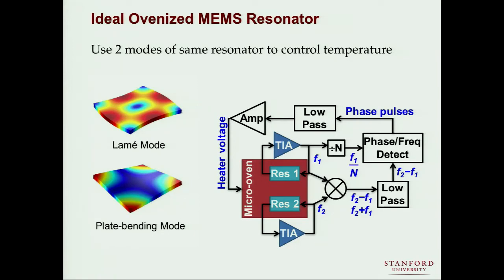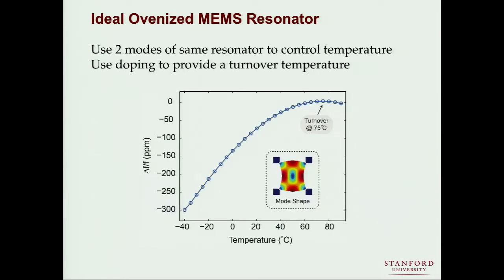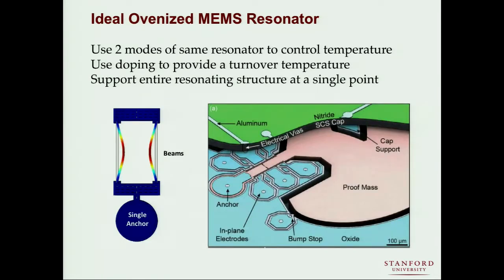You don't want to use a thermistor. You want to use two modes of the same piece of silicon to measure temperature. One mode has a high temperature coefficient, one mode has a low temperature coefficient. You implement a loop around some relationship between those modes. You want to use this doping technique I mentioned to give you a nice flat spot somewhere on the temperature dependence of the dominant mode of your system and operate at that point. So you correct first order all of the temperature effects. You want to support the whole thing with a single anchor. Don't build a web. Have a single point.